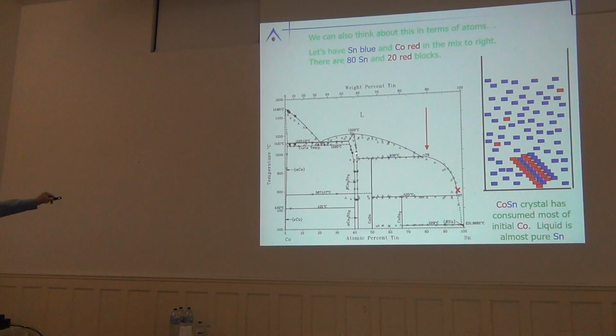What's happening is I'm growing a compound that has a much more cobalt-rich stoichiometry than my initial melt. Therefore, as I grow this 1,1 compound, I'm depleting the cobalt out of the melt. That's what's happening as I go down this liquidus line. Okay? That's the essence of solution growth.